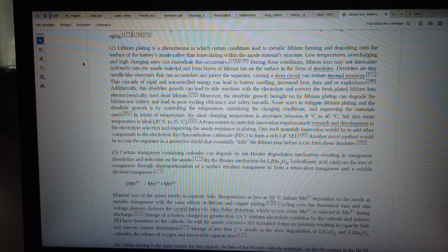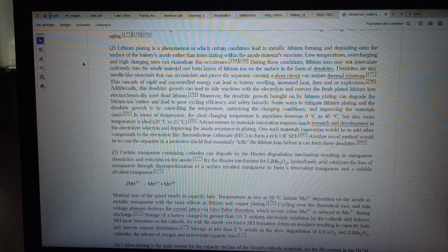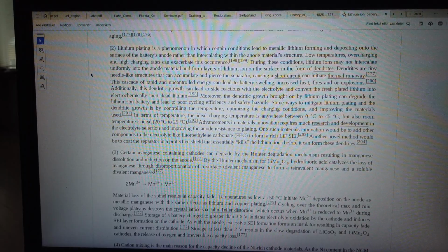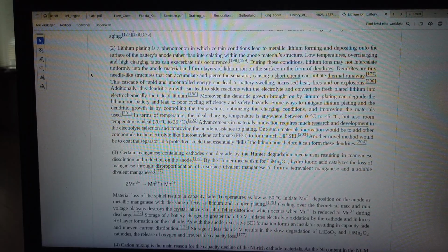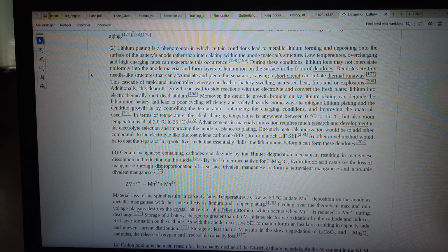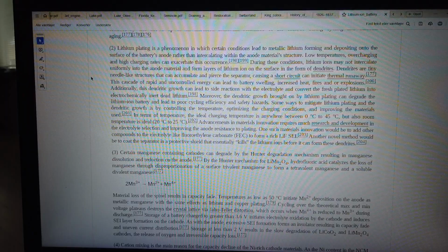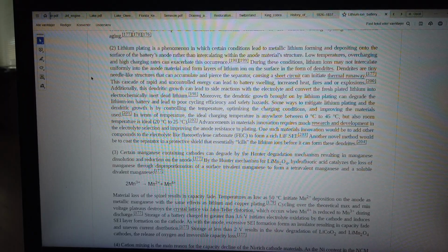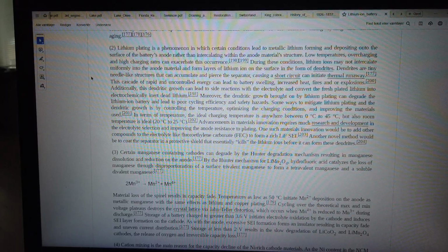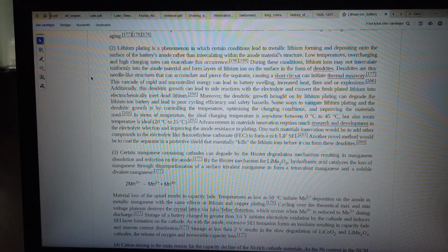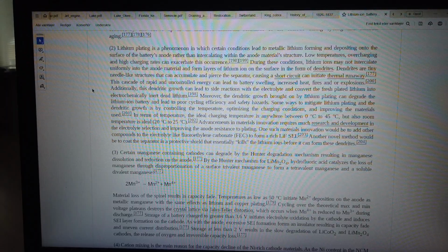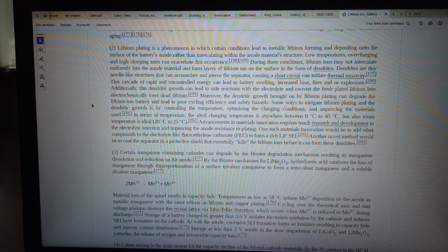During these conditions, lithium ions may not intercalate uniformly into the anode material and form layers of lithium ion on the surface in the form of dendrites. Dendrites are tiny needle-like structures that can accumulate and pierce the separator, causing a short circuit that can initiate thermal runaway. This cascade of rapid and uncontrolled energy can lead to battery swelling, increased heat, fires and/or explosions.